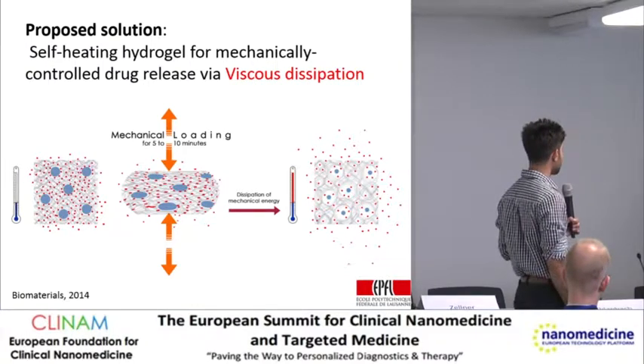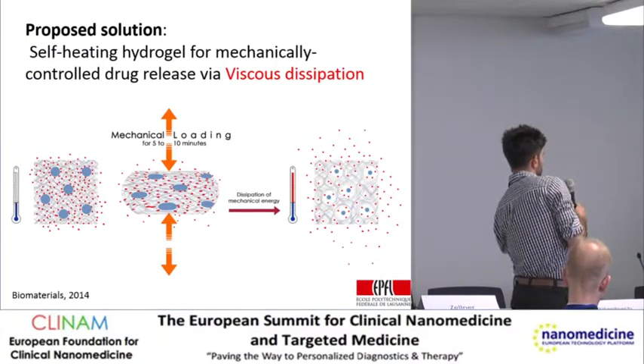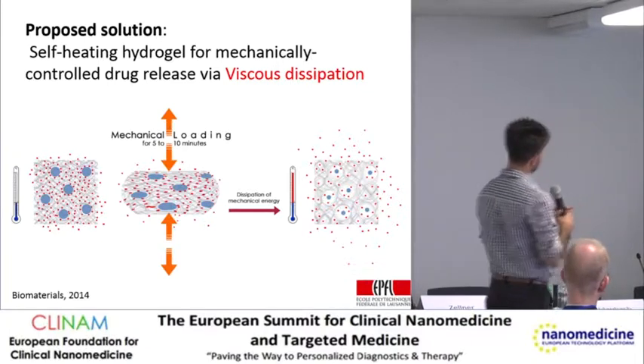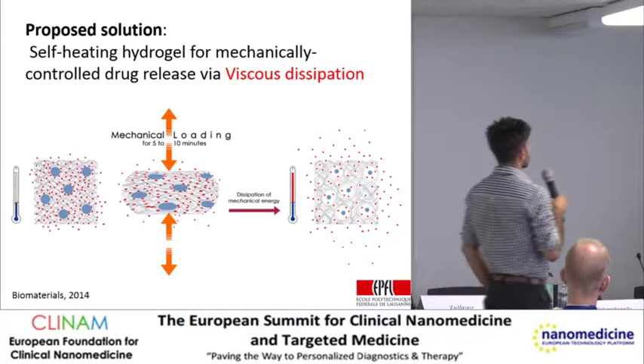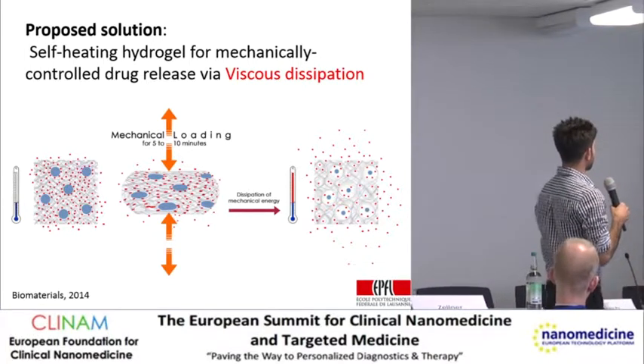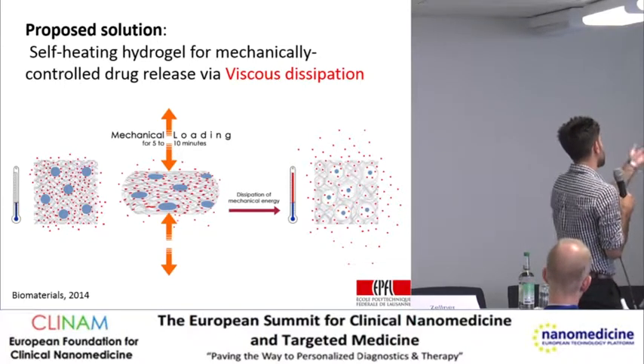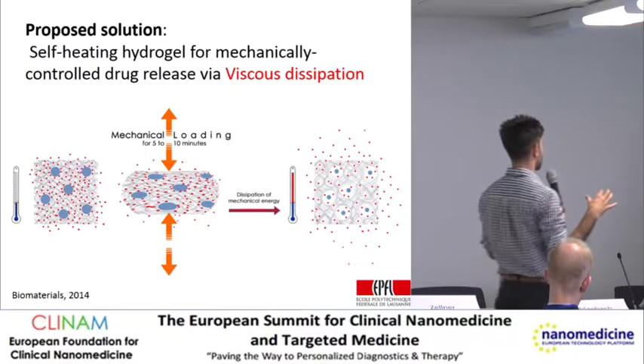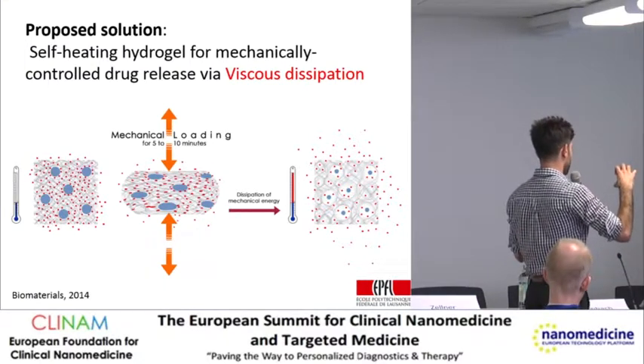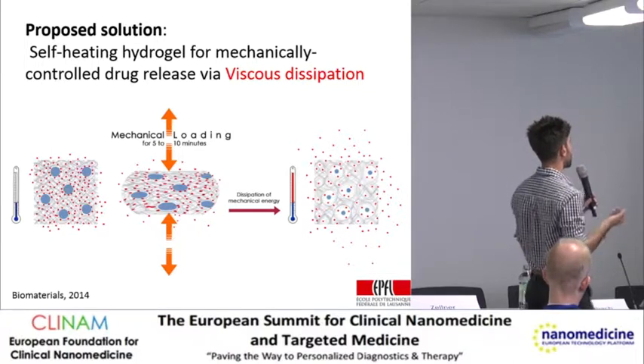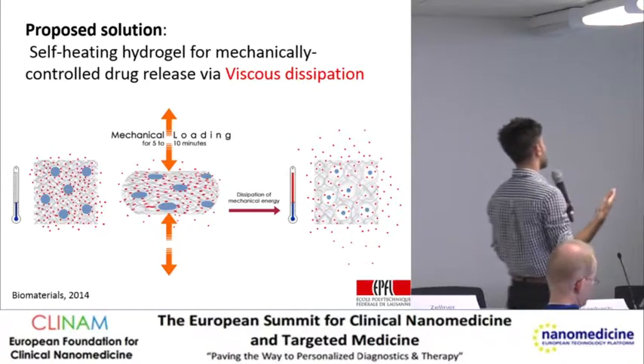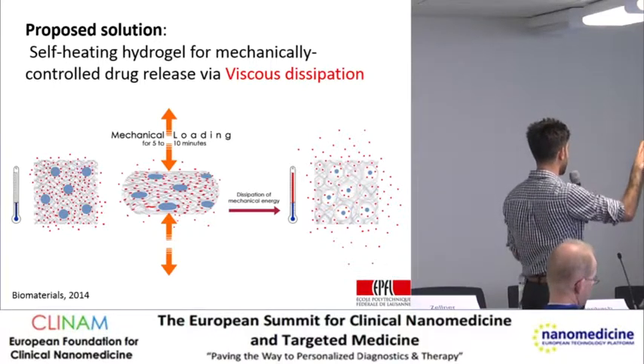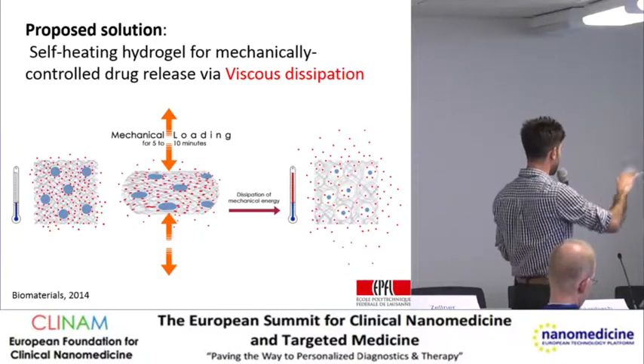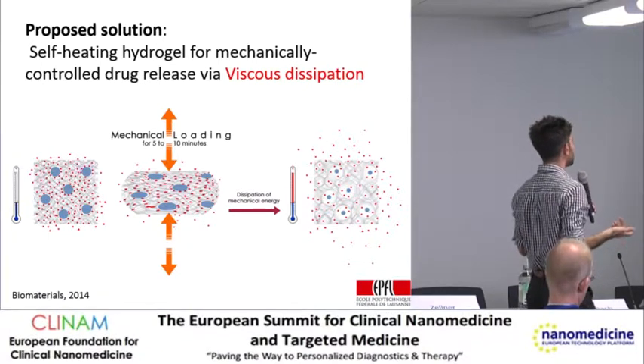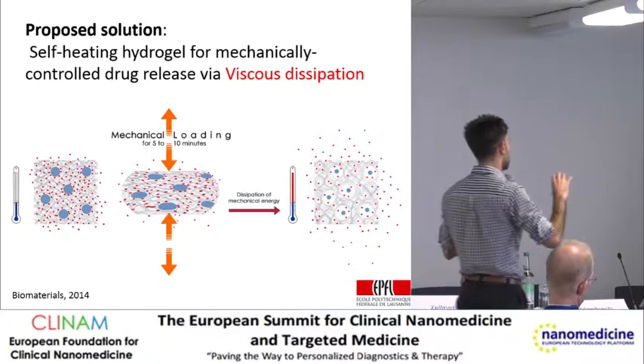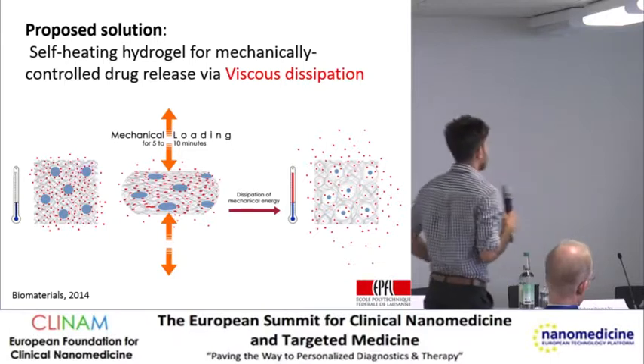Do you have any idea of how efficient this energy conversion is? You're converting mechanical energy into heat. What fraction of that energy goes into heat? Yeah, that was the most challenging work for this hydrogel, that you should play with the structure. As I told, we have to use very low cross-linker that provides high friction, and in this case we had a damping ratio, the coefficient that is the ratio of dissipated energy to the total input energy in this gel, of 0.8, meaning that 80% of the energy is dissipated. 0.8, it's very high. Yeah, extremely high. Oh, that's excellent.